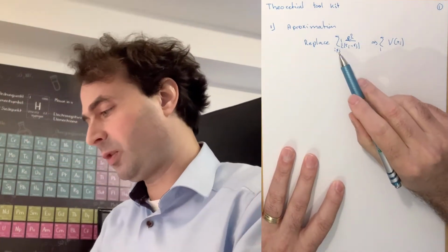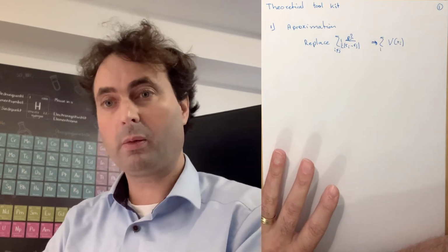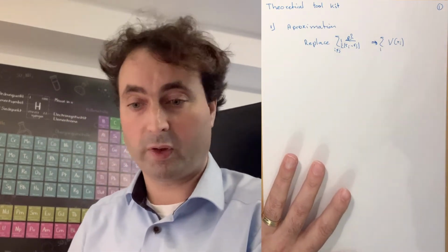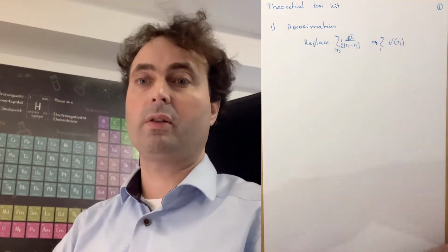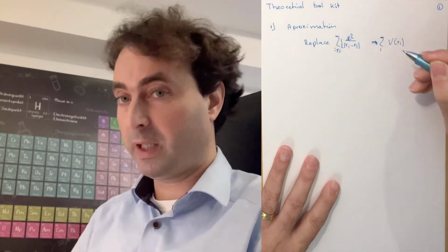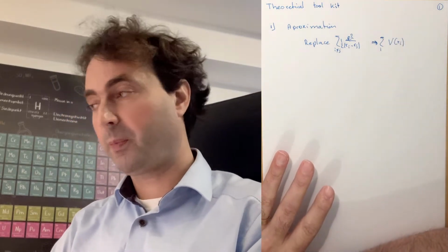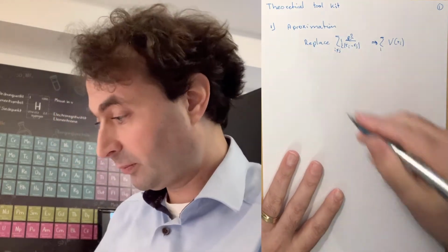And this change from a sum over all pairs to just a sum over one electron helps to remove entanglement between your electrons, because for many electrons moving in a potential, you can always find a representation of your wave function that is given by a single Slater determinant. Then on that basis there is no entanglement, and that hugely simplifies the problem.